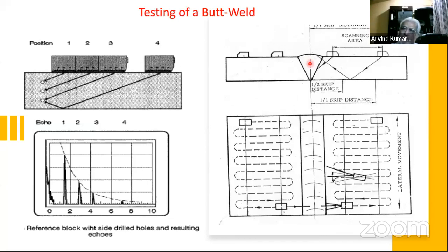Now the good practice is, if it is a butt weld which is accessible from both sides, you have to do the scanning from both sides. Although from one side I'm able to cover the entire weld, we do not know the orientation of the defect and all that. So it is better to check from the other surface also in a similar fashion.